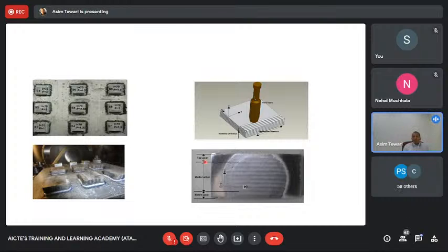If you constrain it or you self-constrain it, then it would lead to elastic strains, which is nothing but the total strain minus the eigenstrain. And that leads to residual stresses. Residual stresses can be mitigated by heating, by heat treatment, and by strategies of additive manufacturing.